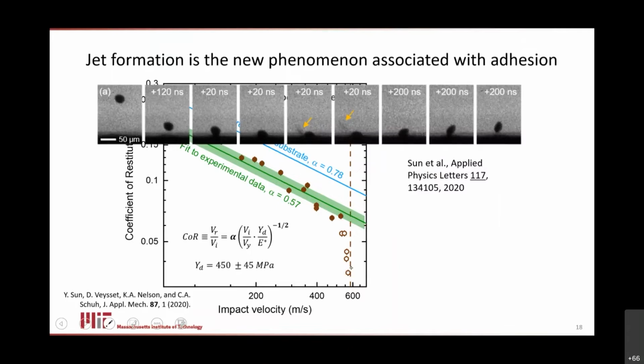Yu-Chen Sun, who's actually a new employee there at Livermore, he had this very famous set of photographs that he took because this is now catching the whole thing in the act. So this is for a shot that's in the middle here. It's in this zone where particles bounce, but they still exhibit jets. And so this particle here with a 20 nanosecond resolution, he captured a jet happening, and even though there's a jet, this particle is still bouncing away. So this is the range where jetting starts, but not enough yet to produce sticking of the particle.